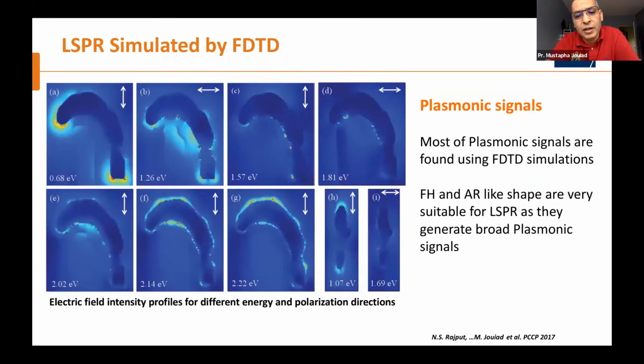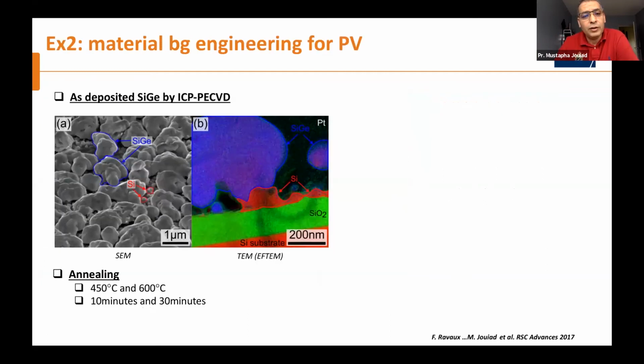FDTD simulation rendered exactly the same response as we obtained in experiments. So we drew this shape in our simulation, and we obtained exactly the same excitation at all energy windows. And this is very interesting. It means that our shape can create the hot electron, which is actually the origin of the high efficiency of our water splitting device. It's reaching 88%. So I finished the first example.